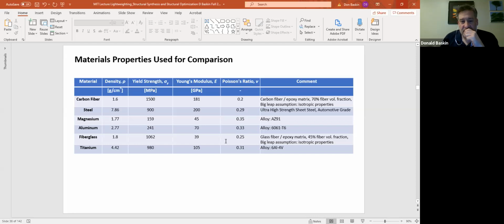Starting at the top, this is a good carbon fiber with about a 70% volume fraction, so that's really, really high volume fraction actually for carbon fiber. The yield strength is about 1.5 gigapascals, and the density is about 1.6 grams per centimeter cubed. The Young's modulus is about 181. Okay, I picked these numbers out of a table. You can go into a book and you can find these values yourself. A medium or pretty high strength steel, but there's much higher strength steel, has a yield strength of about 0.9 gigapascals or 900 megapascals, a density which is actually pretty high of 7.86, a Young's modulus of 200.